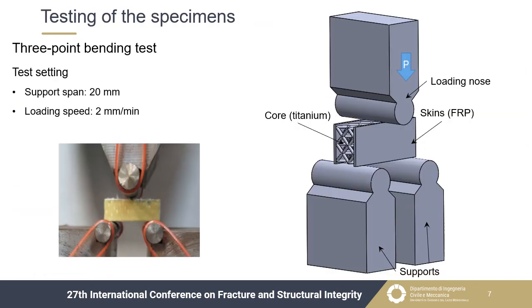The produced specimens were tested according to the 3-point bending scheme. The specimens were placed on two supports and they were loaded in the center by a loading nose. This test is commonly used for sandwich structures, but usually the out-of-plane properties are determined. As aforesaid, in this work the in-plane characteristics are studied. Therefore, the load was applied perpendicularly to the skin direction, as visible in the figure. The span length was chosen equal to 20 mm, while the loading speed to 2 mm per minute.